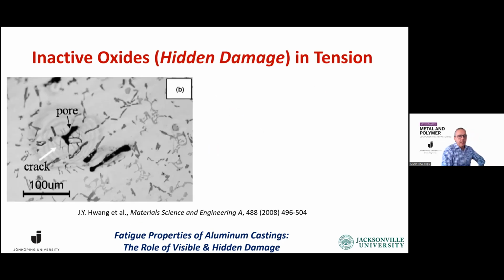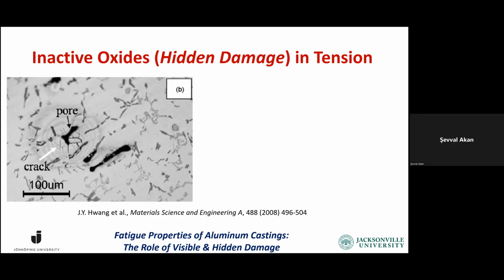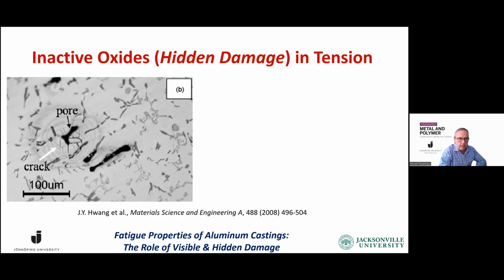Okay, so yes, we can hide the damage, but there is one thing that the invisible damage can never hide from, and that's a tensile stress. They cannot withstand the tensile stress. So here's an in situ tensile test. You see a pore, and at a very low stress, you see multiple cracks presenting themselves around the pore.